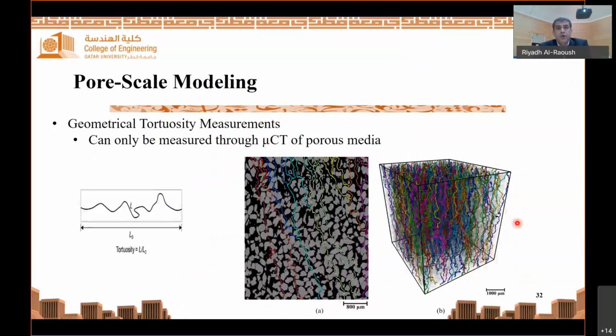Here we use computed tomography to obtain three-dimensional, non-destructive measurements of tortuosity of soils. Tortuosity is an important pore scale parameter that describes the flow paths in a porous media. So you can see here, these are the flow paths. This is a two-dimensional cross-section out of this three-dimensional image. You can see that these are the paths if the flow comes in this direction towards this direction here.